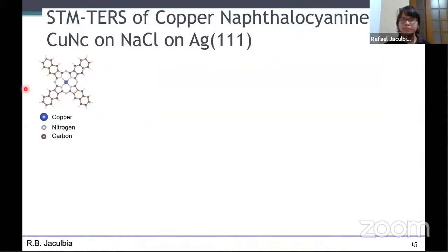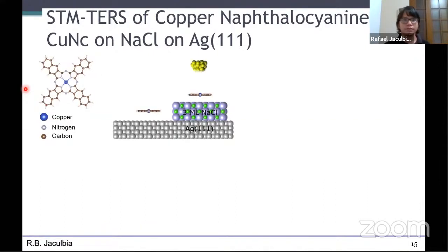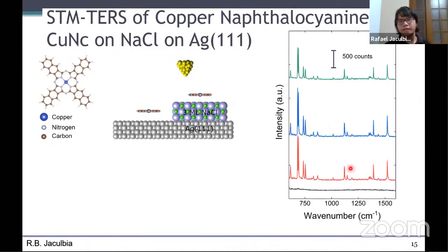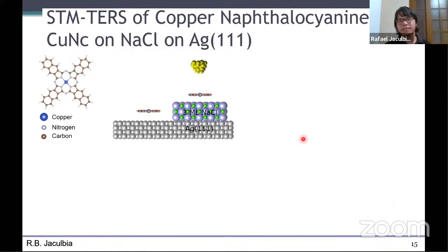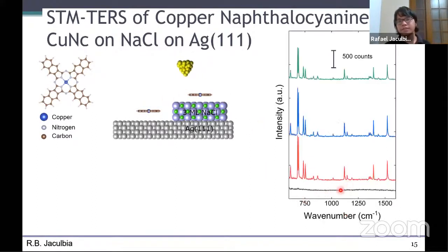Then we measured the Raman signal, the TERS signal, of our molecule. We put the tip near the molecule, and when the tip is at the center, there is no signal. But as we approach the tip off center, we can detect the Raman signal. And moreover, away from the molecule, we cannot detect any signal. So basically, this suggests that we successfully got the tip-enhanced Raman signal.